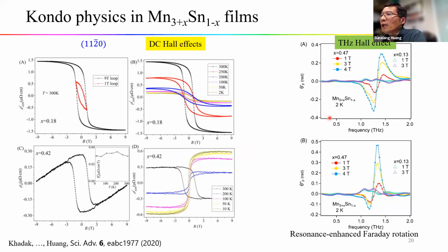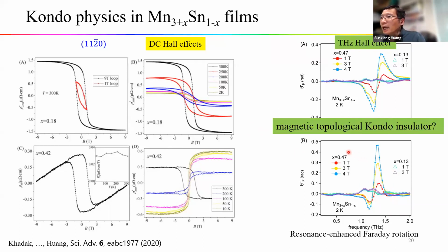However, for this Kondo insulator state, we observe resonance enhanced Faraday rotation. The signal is much larger than in the lightly doped sample, and it depends on the frequency. The resonance happens around 1.3 terahertz, corresponding to the energy gap of 5.5 meV. So that may indicate that for the highly doped sample, we may have some new topological state, which could be a magnetic topological Kondo insulator.